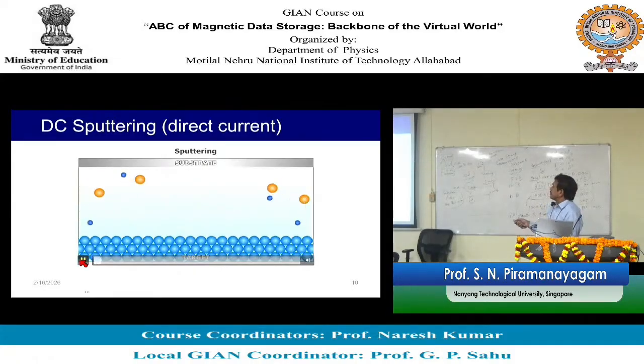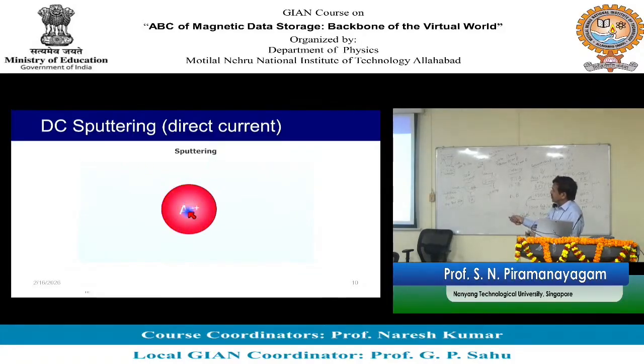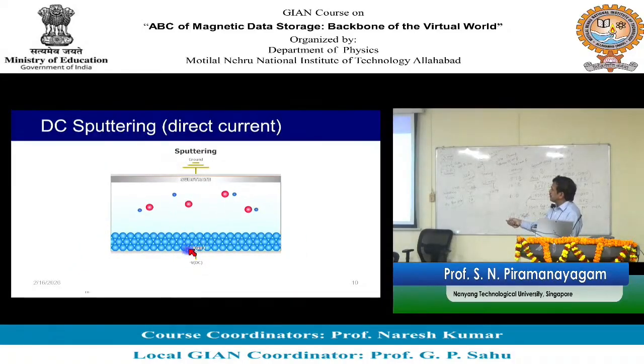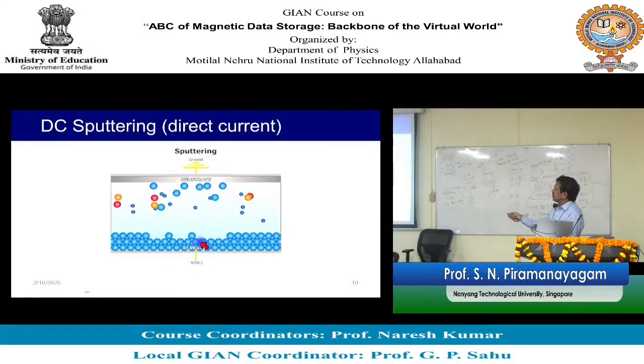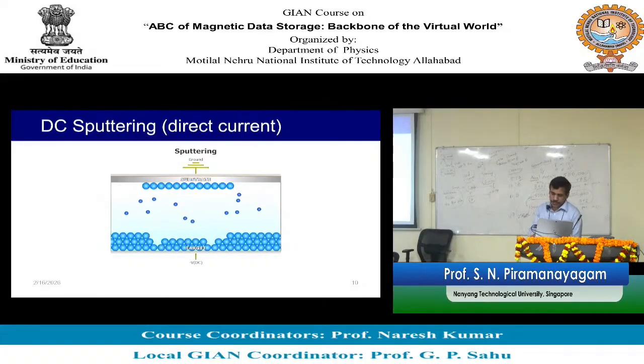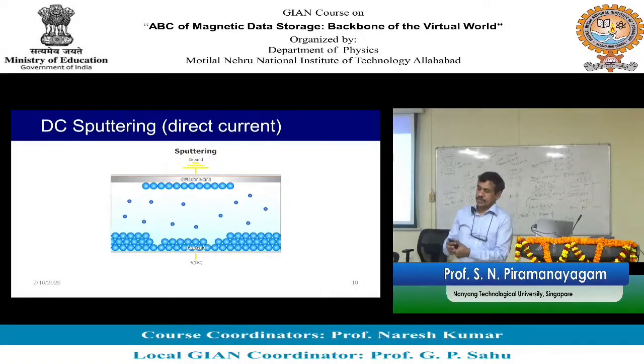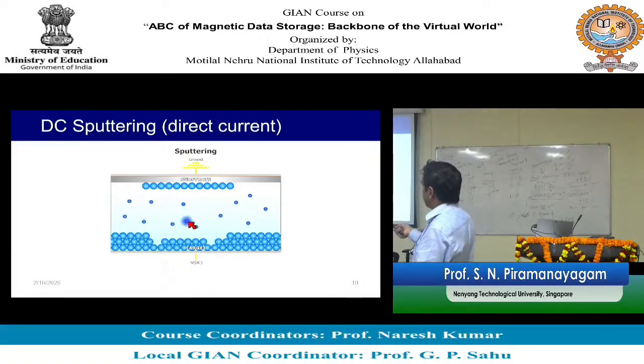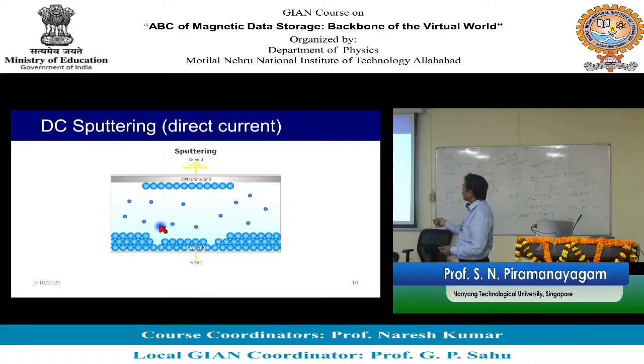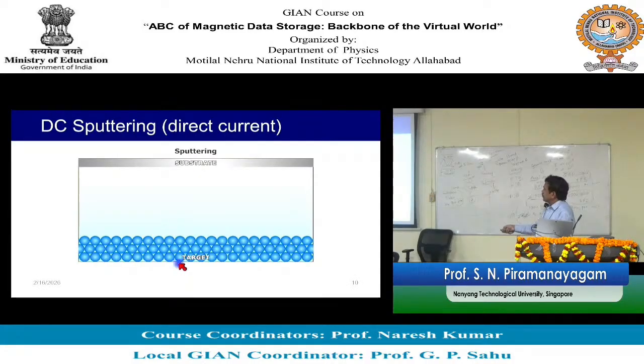I'll repeat again. I send argon gas. Argon gas gets ionized. After electrons go out, you have argon ions. These are positive. This is a negative voltage. Negative voltage will attract positive ions, so they come with some energy and knock off atoms. These blue atoms go everywhere, and they will also get deposited onto the substrate. So this is called a sputtering process. It's a physical deposition. You transfer momentum from the argon ions. It's basically transfer of momentum that releases atoms from a particular surface, and these atoms get deposited onto the substrate. This is called DC sputtering, because we are applying a negative voltage to the target. This is the cathode, and the rest of the system is grounded. With respect to the rest of the system, which is at 0 volt, this is at negative volt. So this is called DC sputtering, direct current sputtering.